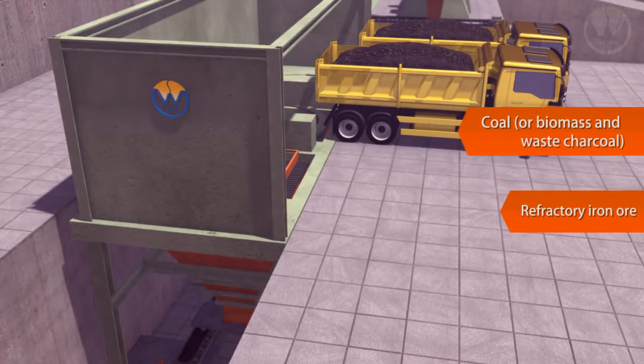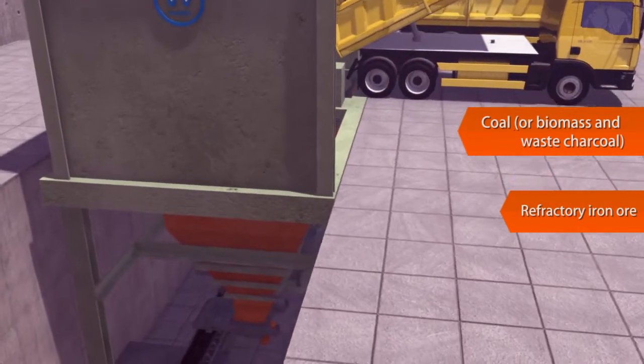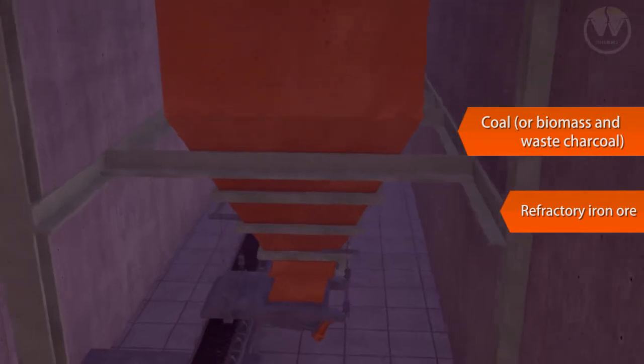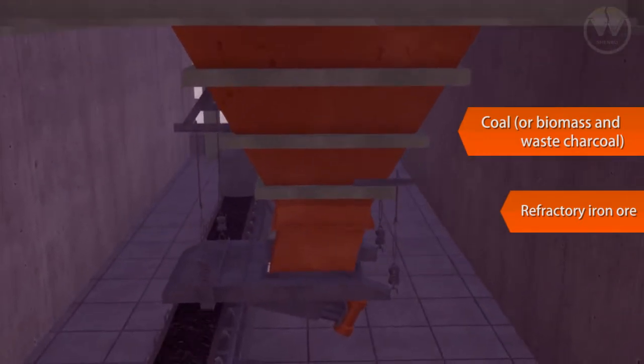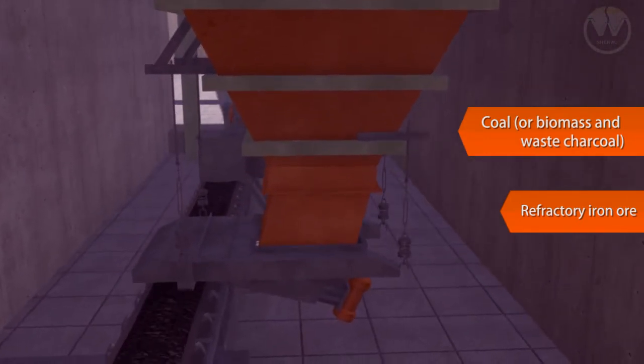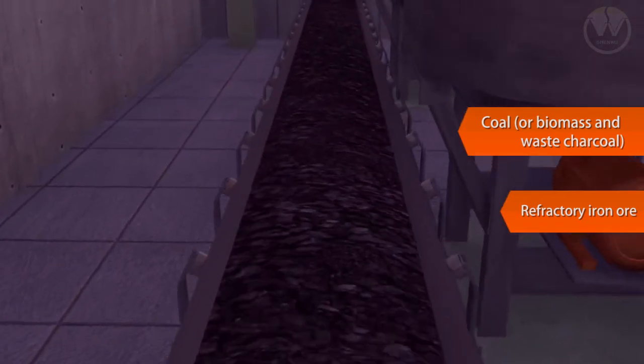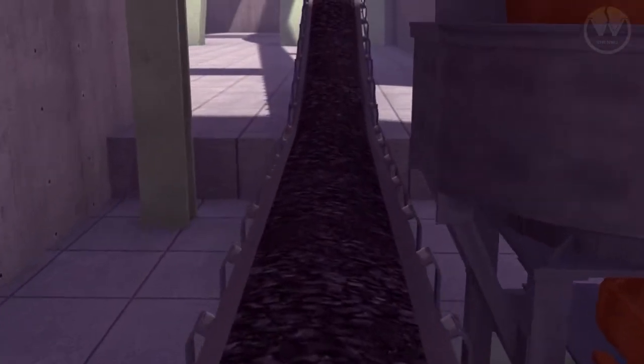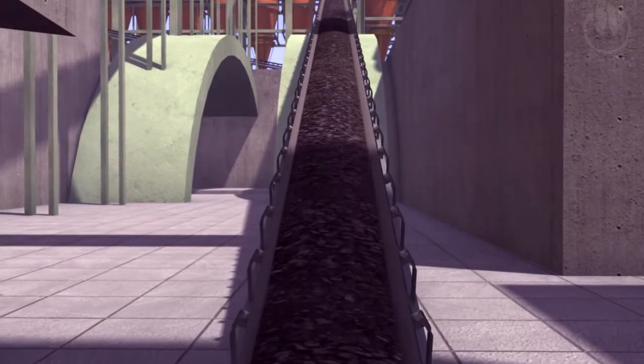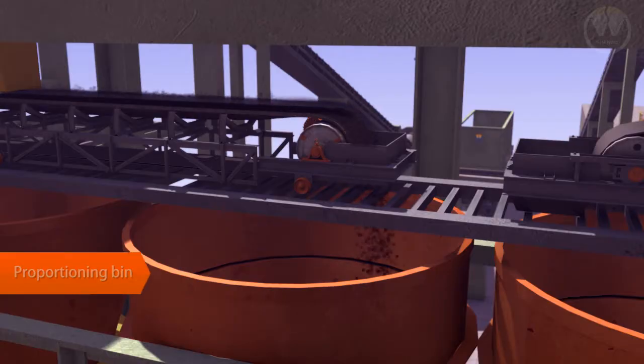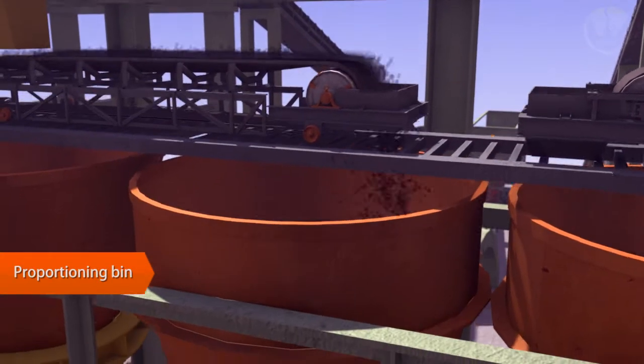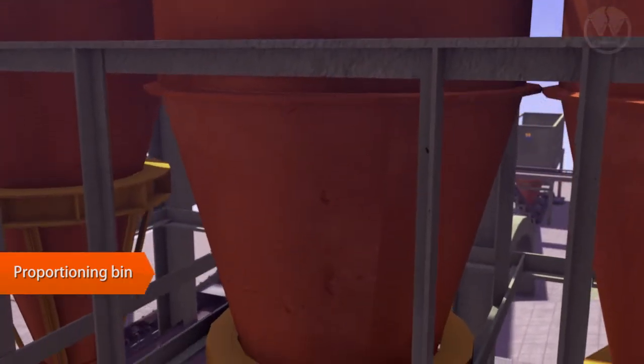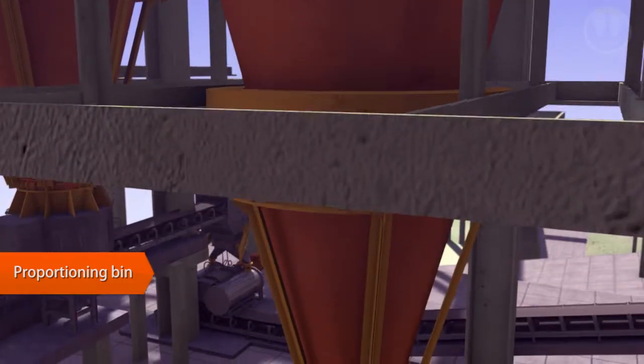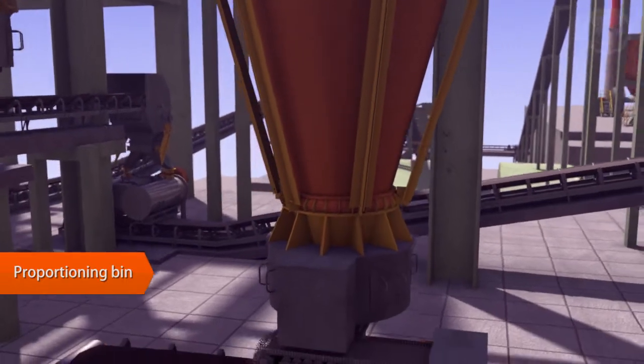Through breaking, screening and fine grinding procedures, raw materials with Fe content from the stockyard will be kept in storage in the feedstock bin. The iron-bearing raw ores and the carbonaceous reductants are uniformly sent to the feed belt via the feeder under the feedstock bin and then sent to the proportioning bin by the belt. A movable belt is set over the proportioning bins so that the materials can be easily stored in each of them.